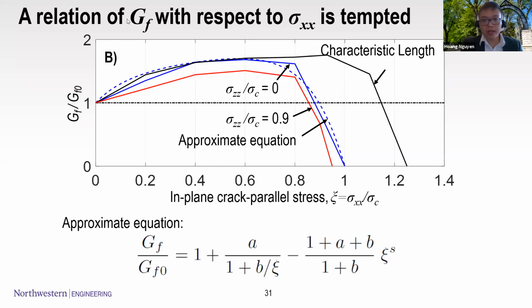So, okay, now we see that GF depends on sigma xx, and any cohesive zone crack model and LEFM-based model cannot be used if such a phenomenon is simulated, right? So we can still use a cohesive zone model or a crack model with the GF modified as a function of sigma xx, and from the shape of the curve, we propose a form of the function of such a dependence here.